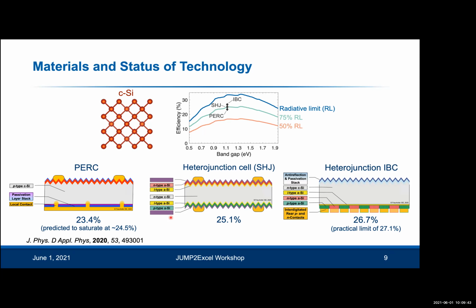And on the bottom here, you can see three common device structures for silicon photovoltaics. Right now, the most commonly used one is this PERC structure. PERC stands for passivated emitter and rear cell. So the name tells you what it's all about. It's about passivating both the front and the back contacts, so you can passivate these dangling bonds and minimize surface recombination.